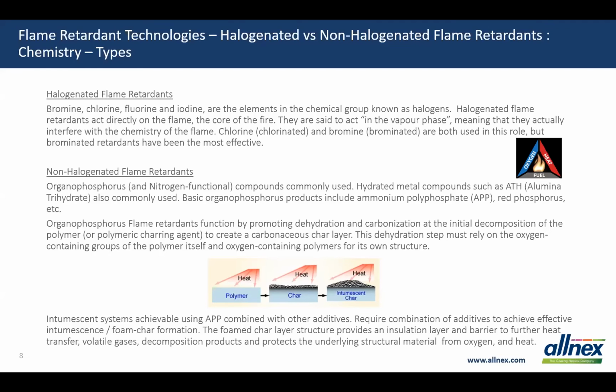So they have a kind of a neutralizing effect and they form halide compounds. What this does is effectively stops the exothermic processes in the fire, the radical formation, which results in an overall cooling of the system, and the supply of flammable gases is also then reduced and suppressed. So if we consider the classic fire triangle, which includes the three components needed for a fire to proceed, heat, oxygen and fuel, we can say that halogenated flame retardants suppress the combustion by removing two of these components, which is thereby fuel and heat.